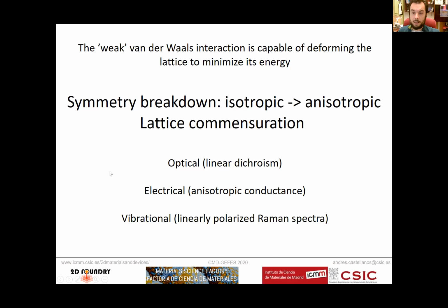And we have seen how this little change in the position of the atoms is strong enough to induce a lot of anisotropy in the system, optical anisotropy. We have seen that the system shows this linear dichroism. So basically, the absorption of the system depends on the orientation of the incoming linearly polarized light with respect to the lattice. We have seen also electrical anisotropy and vibrational anisotropy. And moreover, the optical and electrical anisotropy are closely related. What we see is that we have higher absorption when the light is linearly polarized along the directions with high conductance.